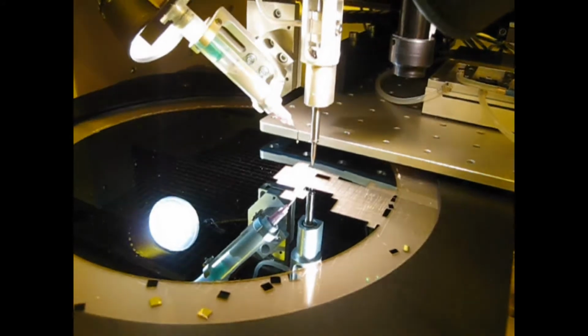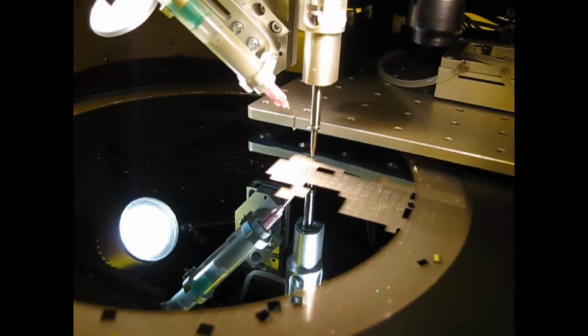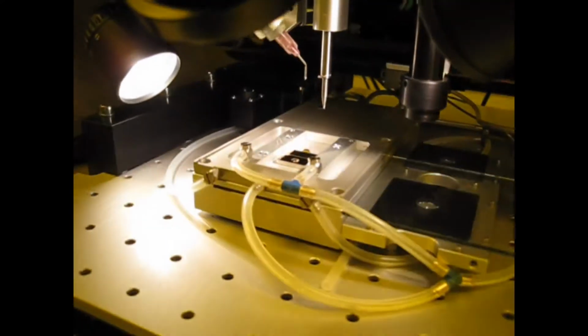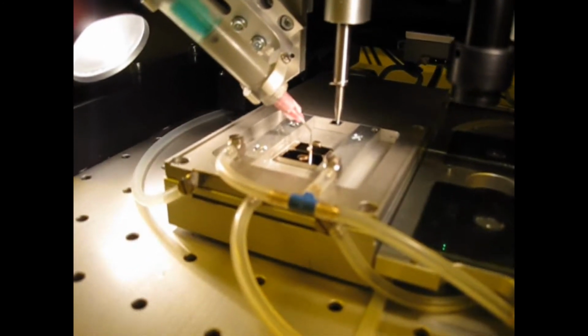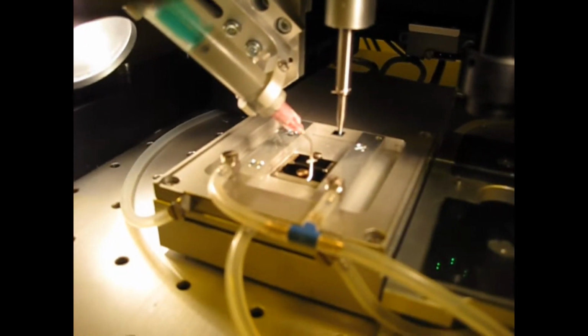Die attachment seems to be a relatively simple procedure, but the requirements are high and quality is critical. Because every chip is handled individually, it has to be a cheap process with high throughput, so that the thousands of chips on a wafer can be processed in a reasonable time frame. For my experiments, I'm using a lab-scale die bonder, which has much lower throughput but allows much more flexibility in the process parameters, such as time, pressure and temperature.